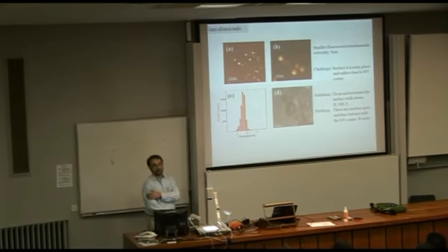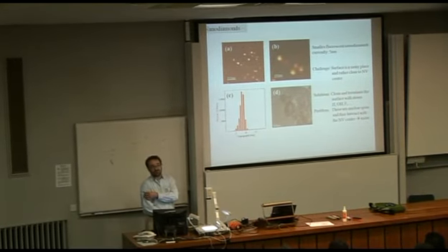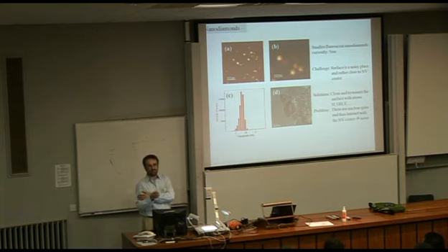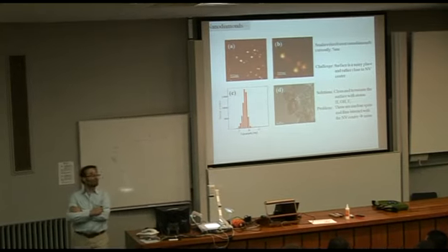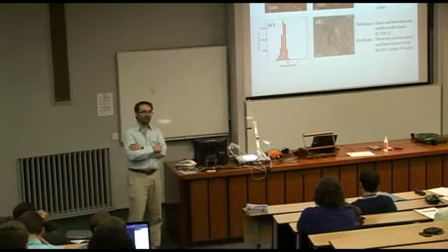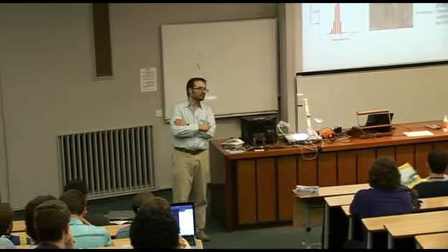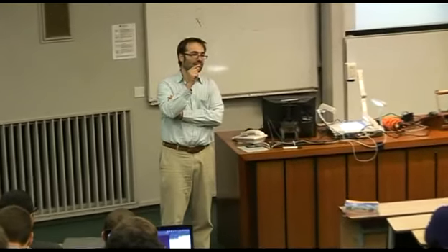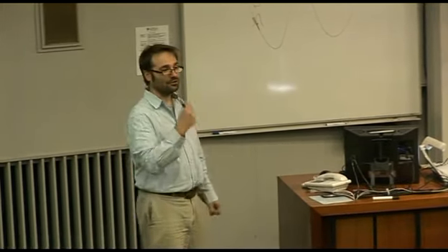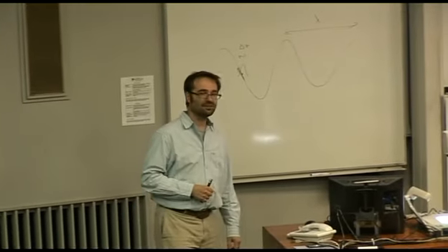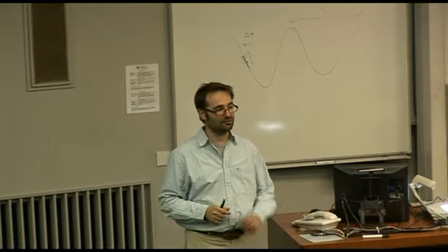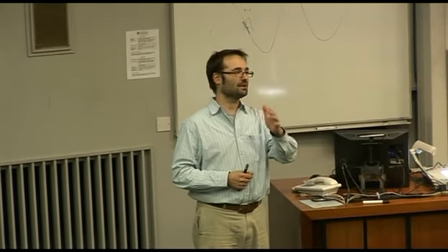But of course, then you also have the problem that not all the diamonds are the same size. Then you have to select them by size, and so there are all sorts of little problems that you still have. But the biggest problem actually is the surface, because it's not very regular. If you take a detonation diamond, for example, then the outer layers are graphite and not diamond, and inside is somehow the diamond. So you have to get rid of this graphite.